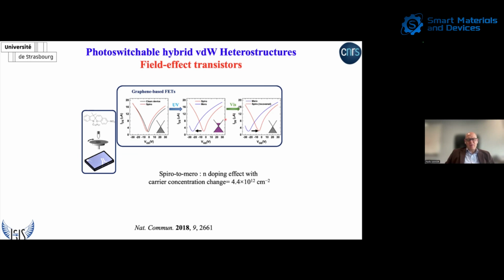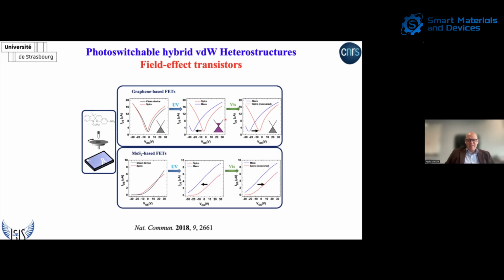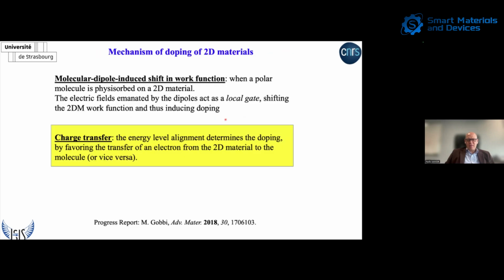And so with a carrier concentration change of 4.4 times 10 to the power 12, which is pretty major. I don't want to emphasize detail, but the very same effect can be observed also on molybdenum disulfide devices instead of the graphene one. Now, let me move to the second type of physical process that can be used to reversibly dope two-dimensional materials. That is charge transfer. This is all about the energy level alignment that determines the doping by favoring the transfer of electrons from the two-dimensional material to the molecule or vice versa.